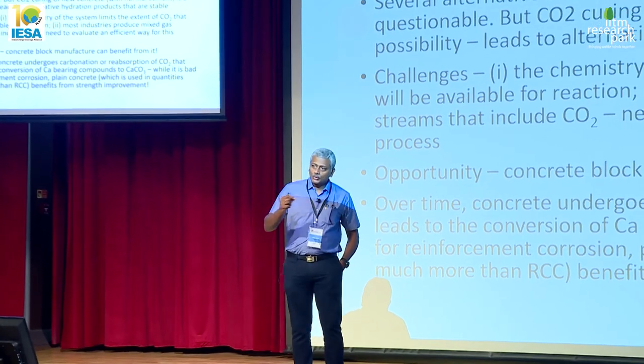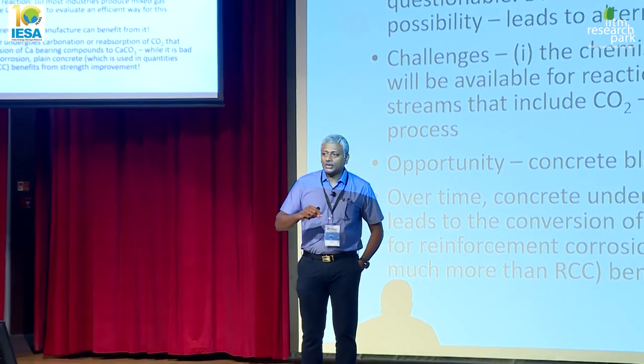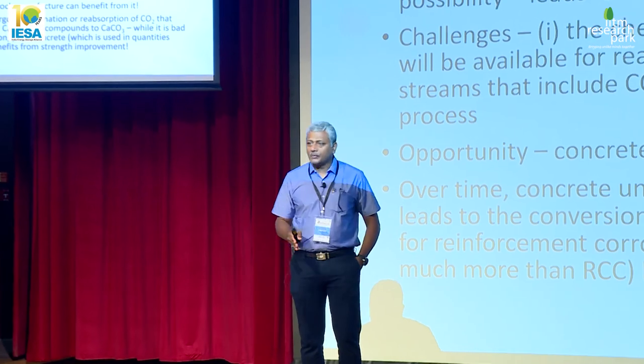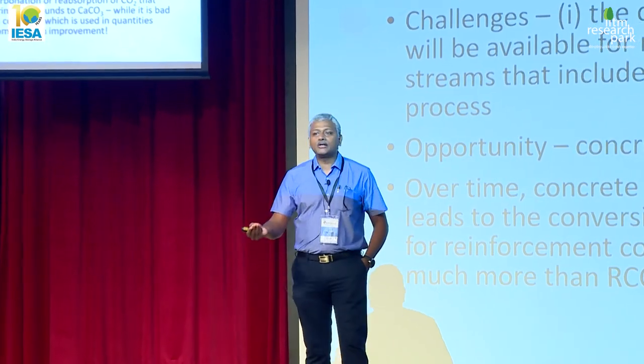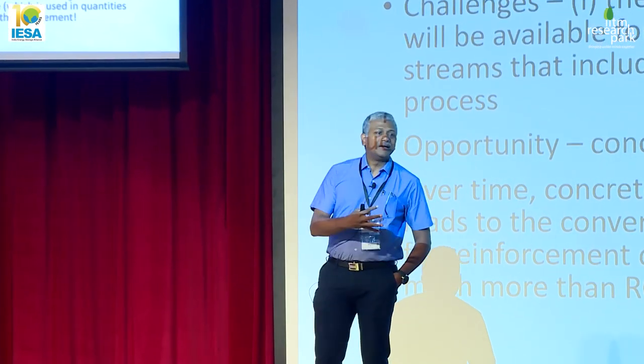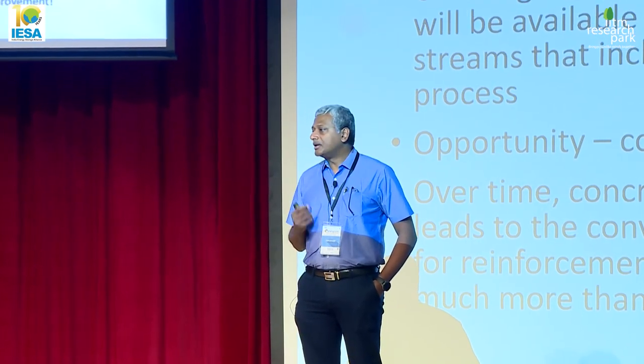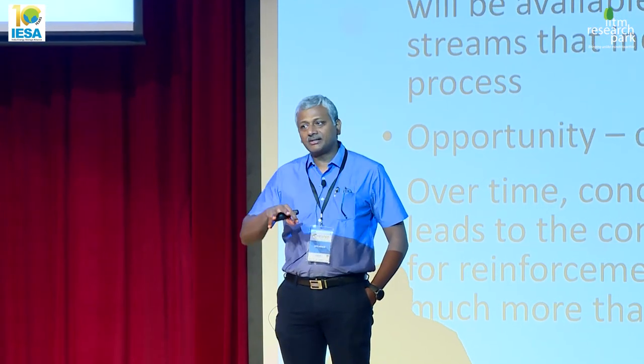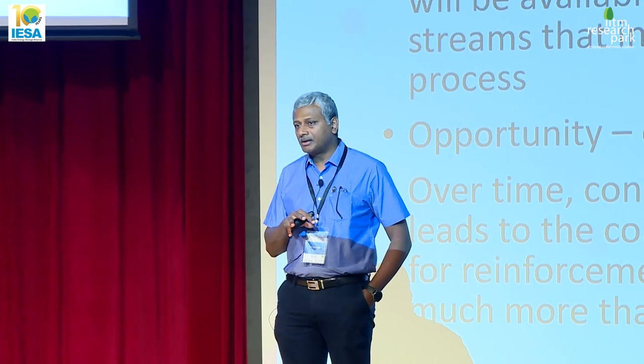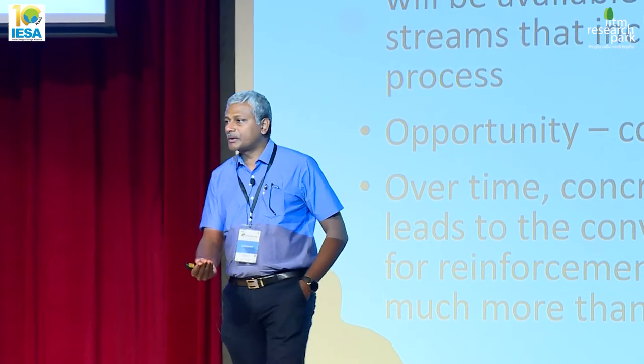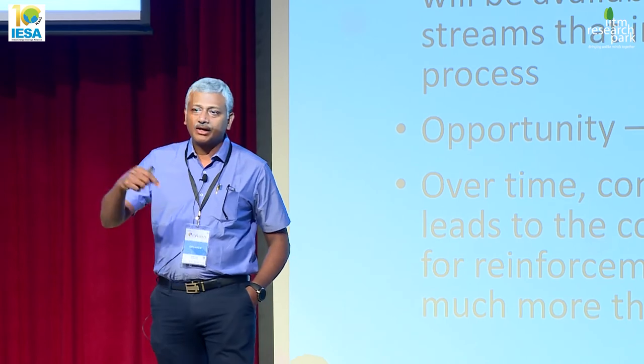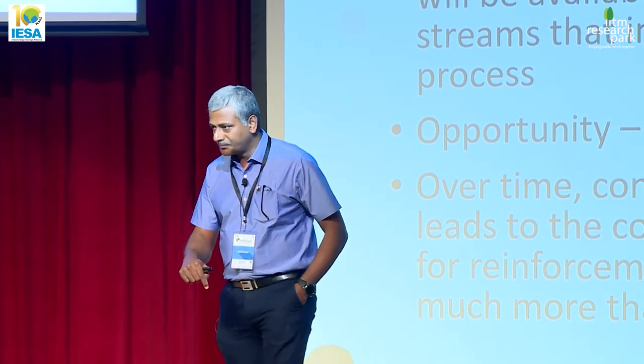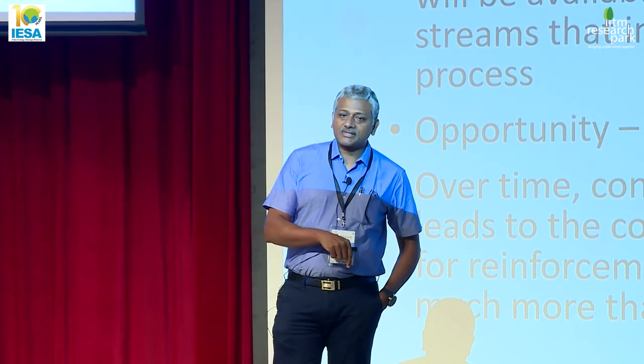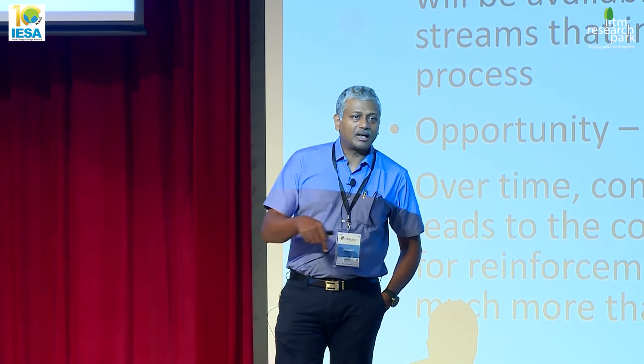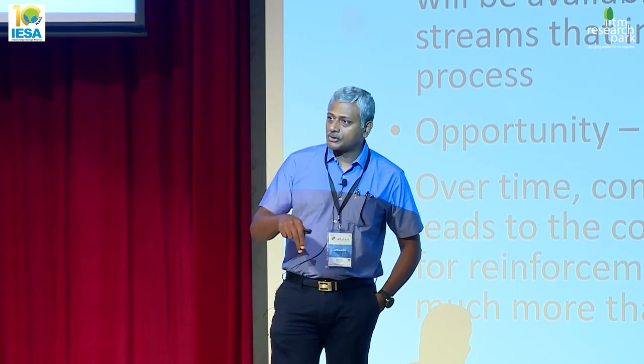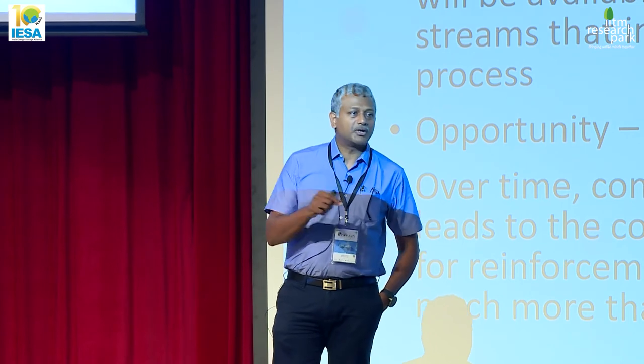So what does CO2 do in new concrete? It leads to a new set of hydration reactions where, along with the calcium silicate hydrate, you also get deposition of calcium carbonate species in the new cementitious components. Now, with this, you are changing the hydration chemistry quite a bit, but how much can you do? That's the question, because CO2 has very limited solubility in water. To react with the cementitious materials, it has to come into a dissolved state with which it can produce these sorts of reactions.